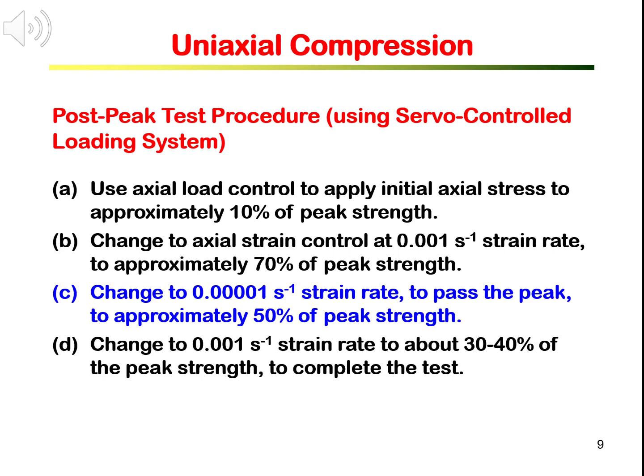We usually stop the test when the axial load reaches about 30 to 40% of the peak strength. Throughout the test, measurements of load and displacements or strains are recorded at 1 Hz frequency. From those recorded measurements, you can generate by computer the complete stress strain curves, including the post-peak part.